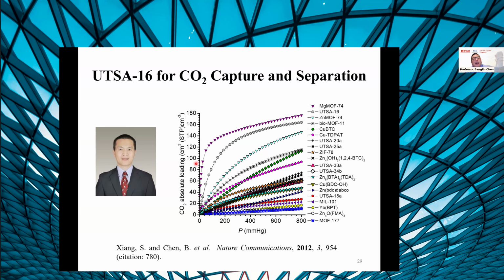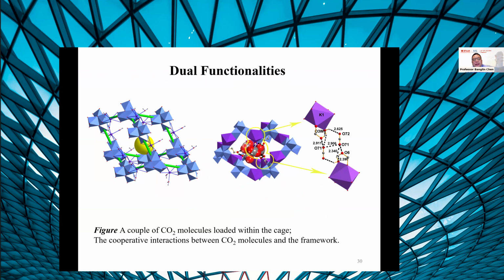So we need to figure out the mechanism why this material is so unique for carbon dioxide capture. Structure study indicated that this pore is suitable, about 4.4 angstrom, 4.5 angstrom, exactly can capture a cluster of 4 carbon dioxide. Furthermore, the terminal water molecule initiates the primary binding site with carbon dioxide, so we call it dual functionality. So nowadays, dual functionality or triple functionality are very powerful strategies to develop gas separation MOF material.